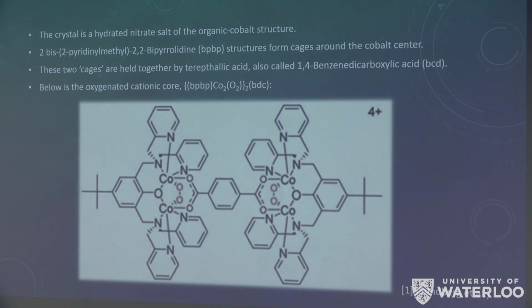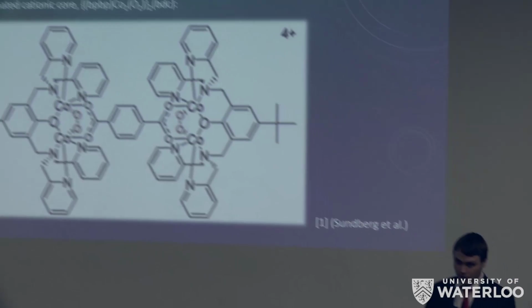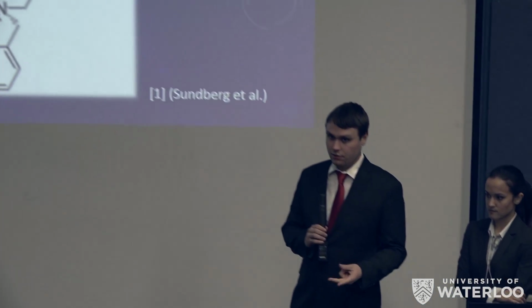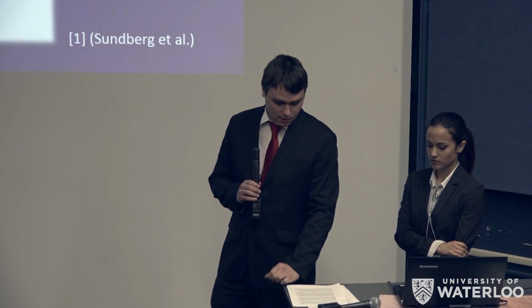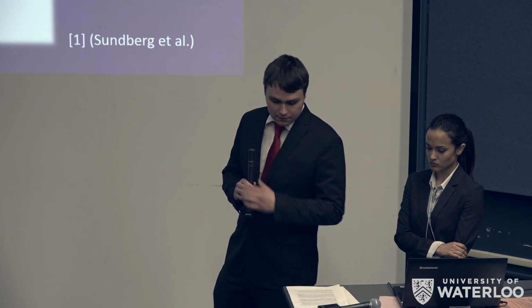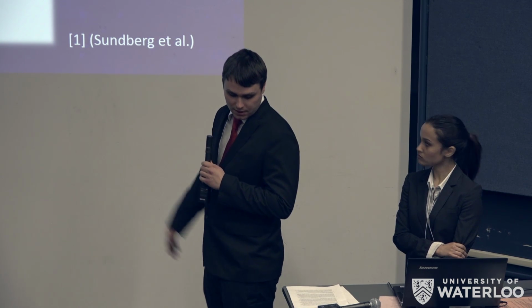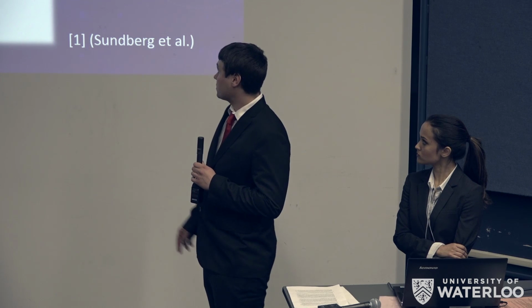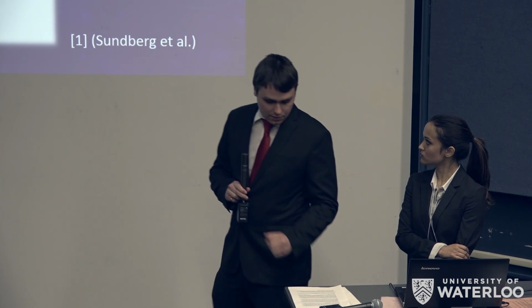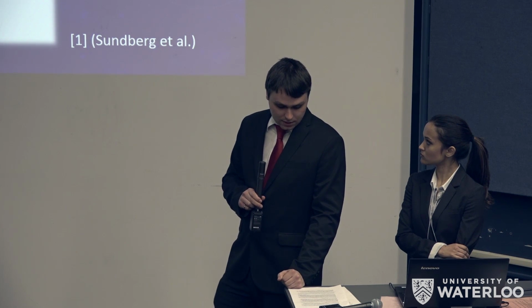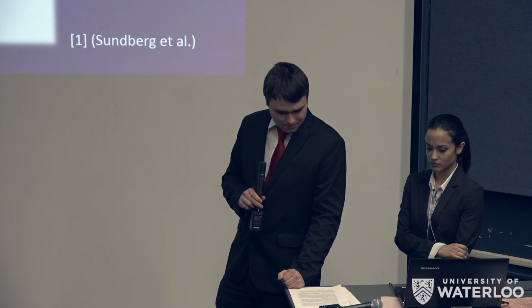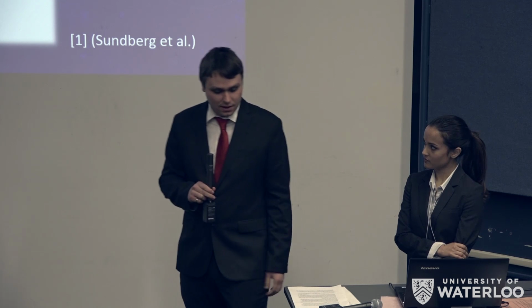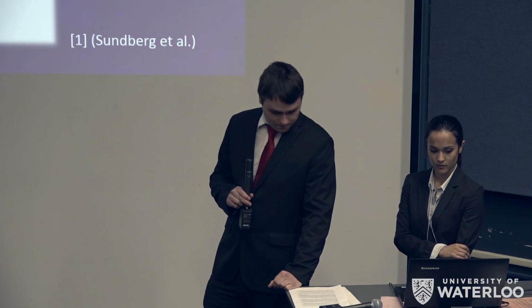This slide shows the active metal organic cation, which is the active center for oxygen absorption. Omitted are the hydrogen atoms, nitrates, and the coordinated waters. So the two halves of our crystal, you can see it's basically a mirror image, consist of the cobalt centers surrounded by a chemical called 2-bis 2-pyridinomethyl 2,2-bipyrrolidine, which we will call BP-BP, structures forming cages.